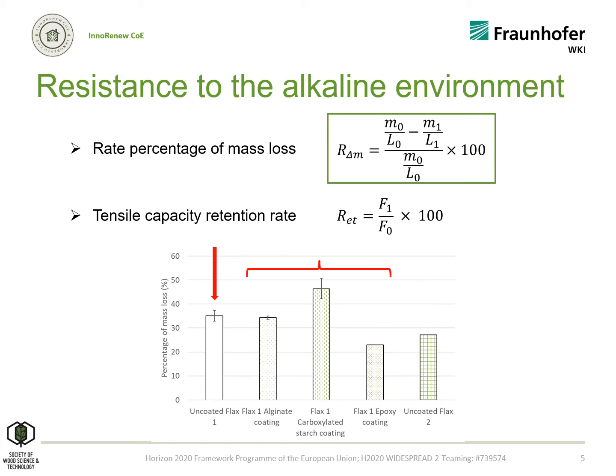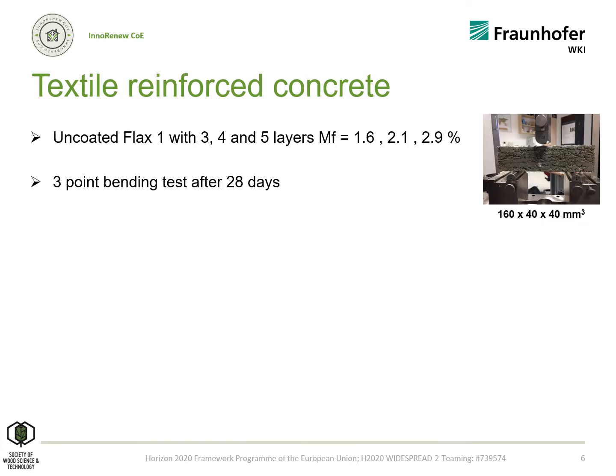Second, the bio-based alginate coating can be interesting because for the same rate percentage of mass loss, the coating will be damaged before the reinforcement. We can also notice that the epoxy coatings bring improvement for this property. The tensile capacity retention rate gives the residual tensile force after the test, but the experiments are still in progress.